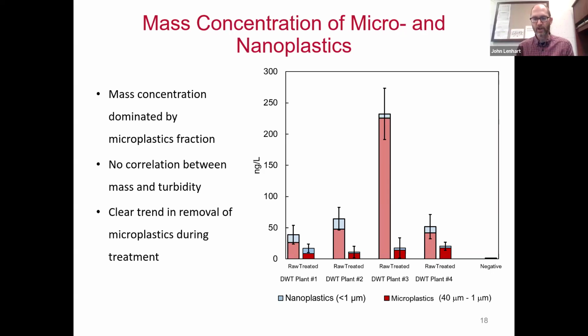I forgot to mention this in the prior slide, but there is a pretty good correlation between particle concentration and turbidity. There is no correlation between the mass concentration and turbidity. And again, in our treated water, we see good removal. In all cases, the actual concentration that we see in the treated water is less than 20 nanograms per liter. So still a very small concentration in terms of the mass of plastics in the treated water.